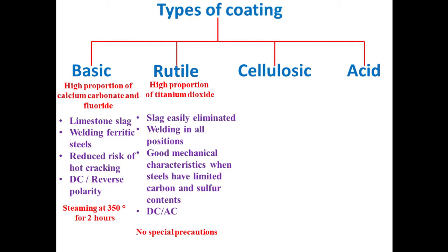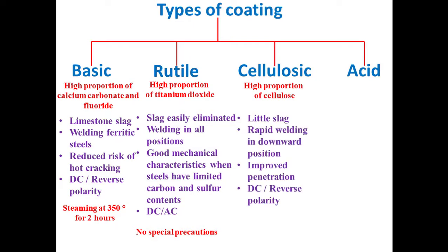Now for the cellulosic coating, it's characterized by a high proportion of cellulose, and it will produce during welding a little slag, and it will permit a rapid welding in downward positions. Also, it's to note that the cellulosic coating will permit an improved penetration, and we should take into consideration that when we weld using a cellulosic coating, it is recommended to use a direct current with a reverse polarity. And it's recommended also to use an open circuit voltage higher than 60 volts when we weld with a cellulosic coated electrode.